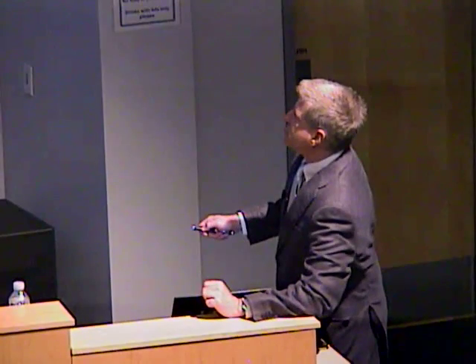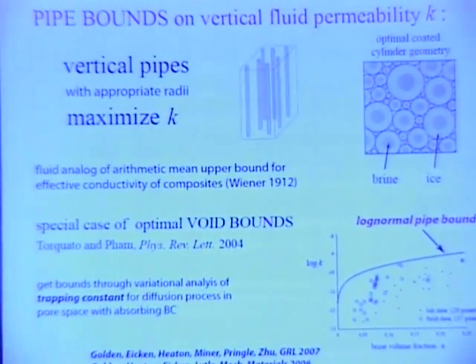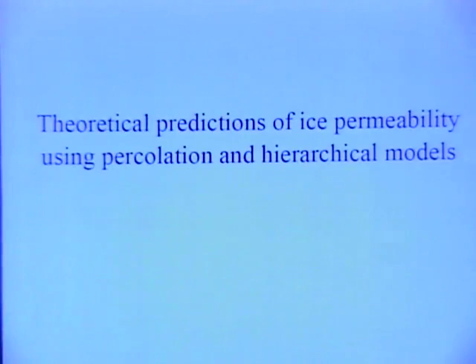This is the fluid analog of the so-called arithmetic mean upper bound for effective conductivity of composites, just the arithmetic average. There was some beautiful work of a colleague of mine, Sal Torquato at Princeton, who derived a more general set of bounds, and it turns out that the bounds we were working with are a special case of his. We get these bounds through a variational analysis of the so-called trapping constant for a diffusion process in the pore space with absorbing boundary conditions, so that's for the mathematicians and physicists in the audience. With such a simple idea, I thought we'd be orders of magnitude off. I thought it would be a bound, but we closely captured all of our laboratory and Arctic data.